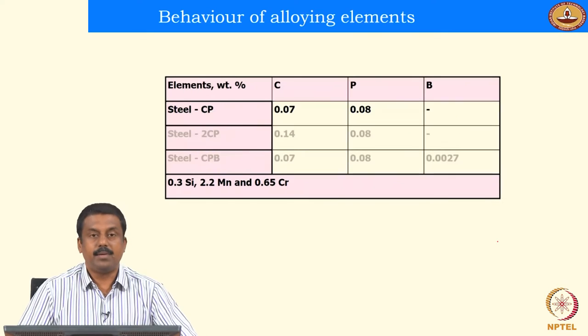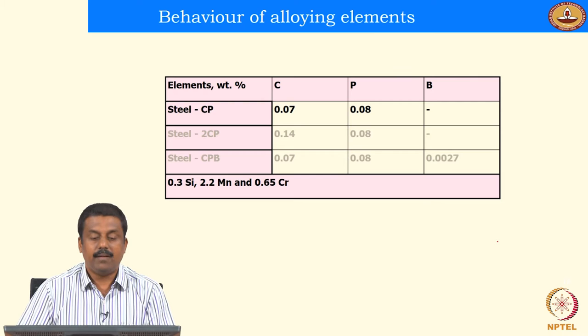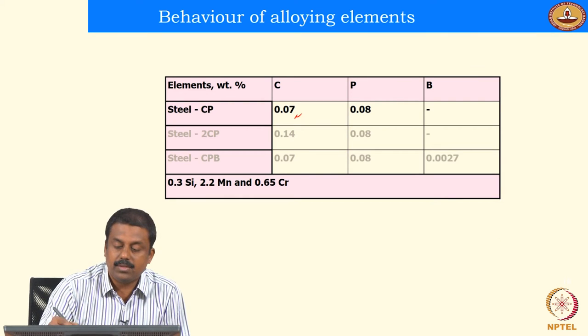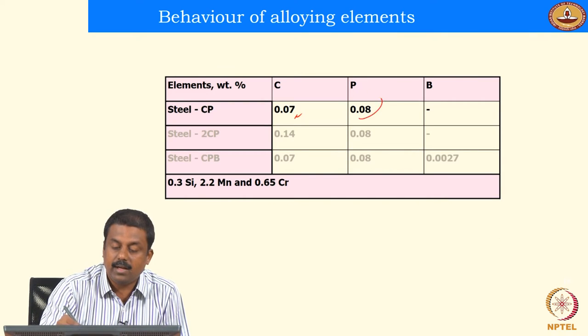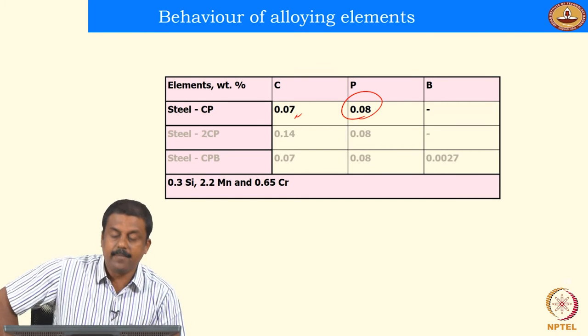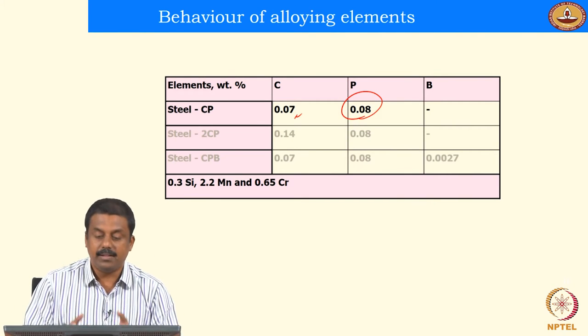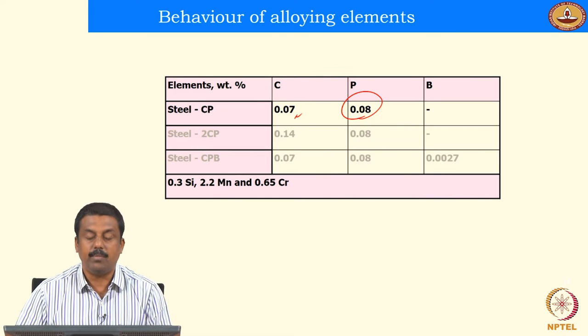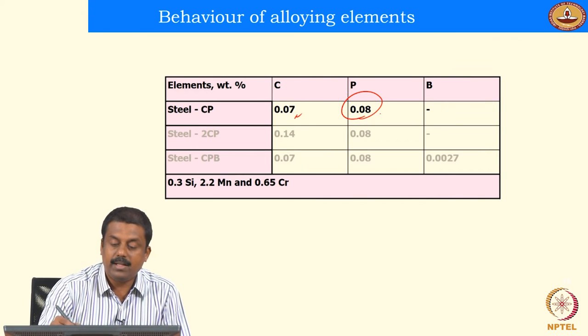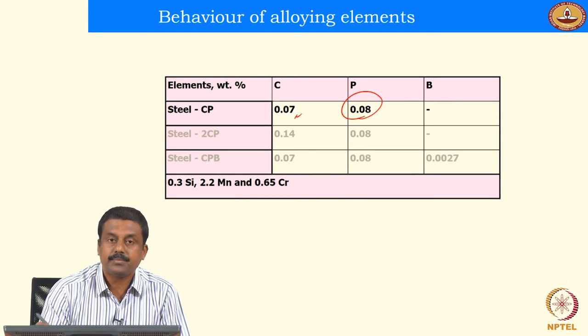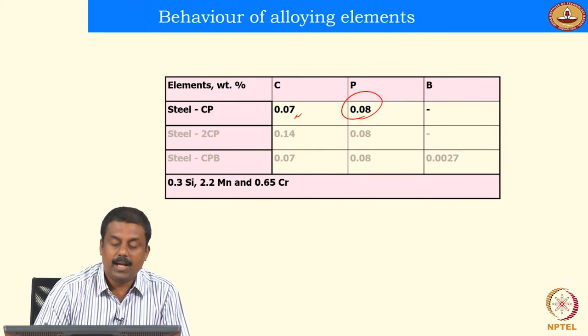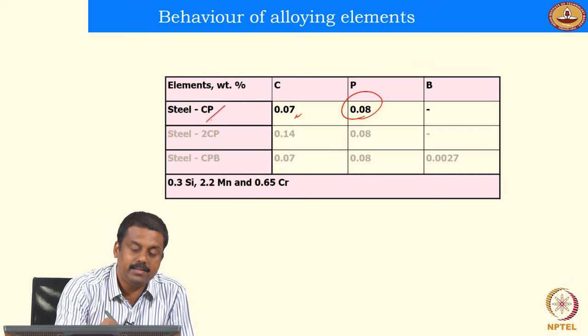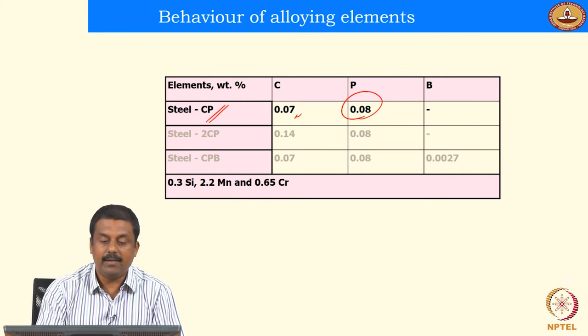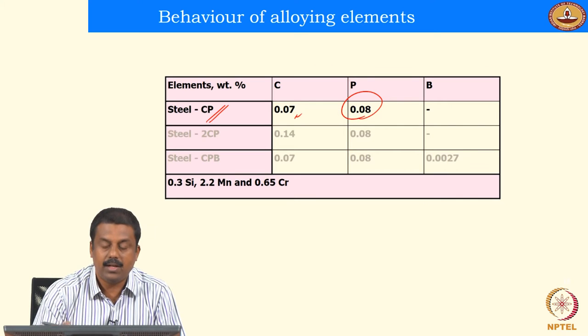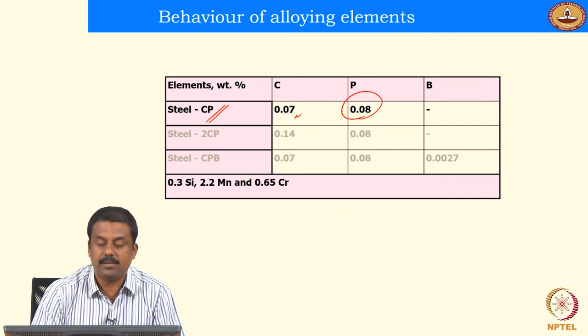We look at the same example steel that I talked about earlier in one of my lectures. We have steels of a low carbon, 0.07, with a very large amount of phosphorus, which is not conventionally added. We just added it to show whether it is possible to generate an advanced high strength steel with a high amount of phosphorus. So we looked at the effect of the phosphorus and boron on the segregation behavior, and we look at one case, for example, only steel CP. It showed the partial plug failure, right? Because of the phosphorus segregation.